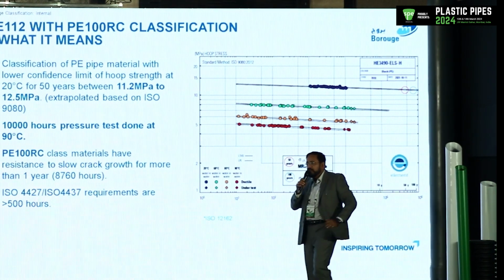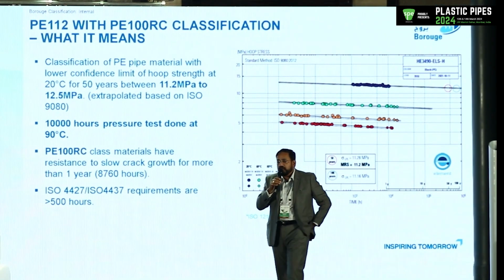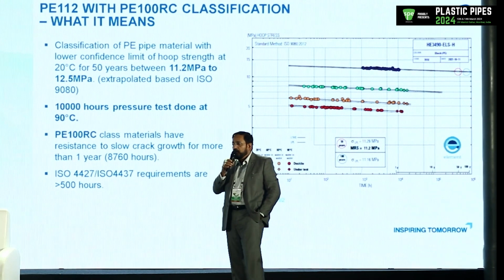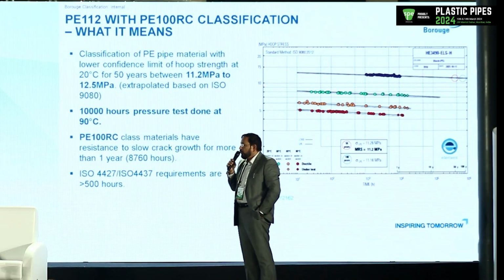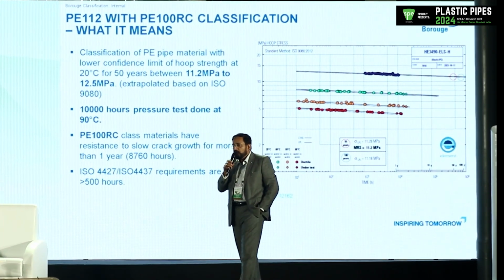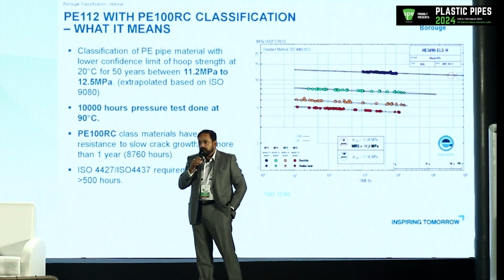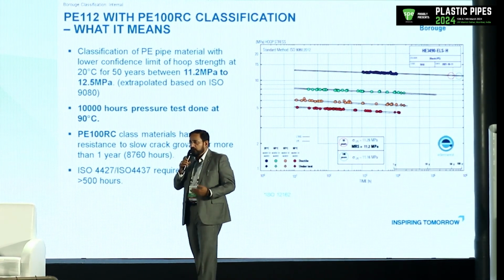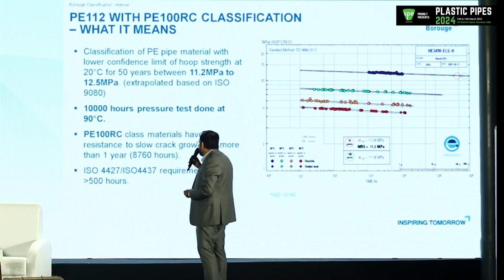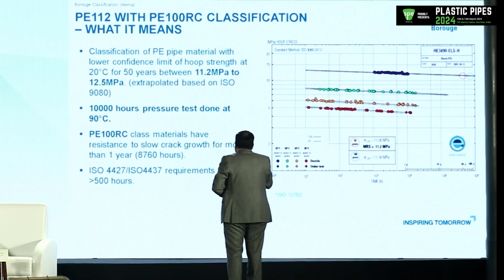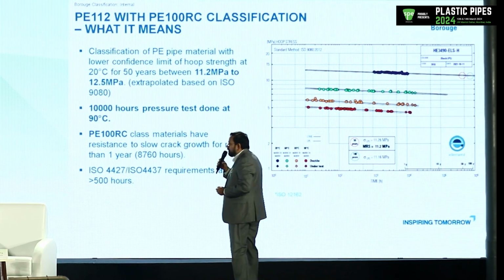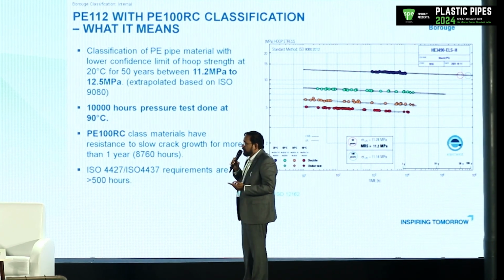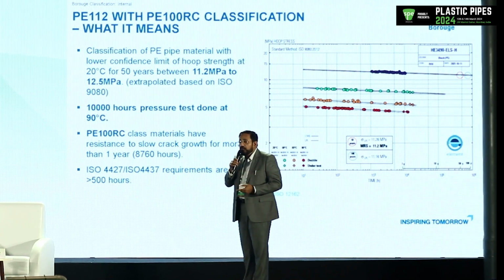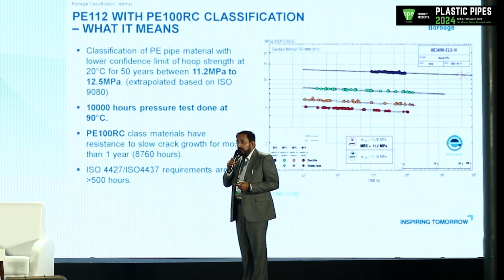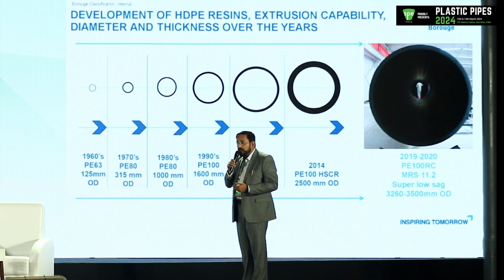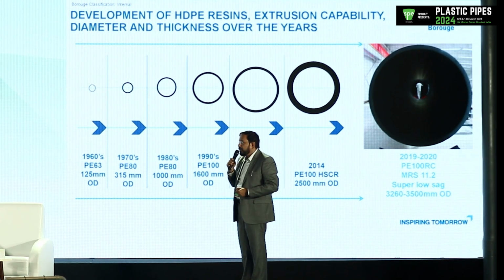So it's wonderful, and that is the topic of the presentation. The theme was sustainability. We are going over and above, and we are talking about 100 years of life. So for the next generation, we are giving a better, far superior material. Also there is a requirement in 9080 that the material should not break. There should be no early failure. Apart from the long term, there should be no failure after 5,000 hours at 80 degrees.